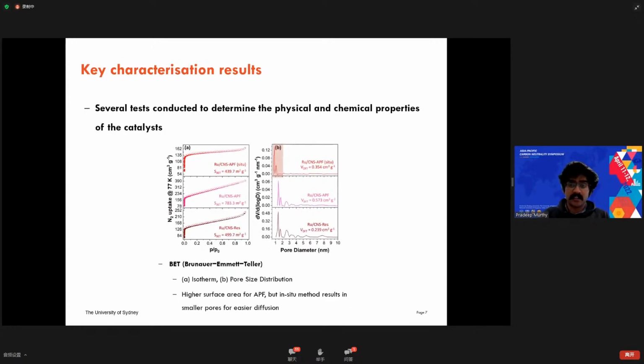We did a BET test. This revealed a higher surface area through using the APF carbon source, but using the in-situ method generated even smaller pores, which would enable easier diffusion of the gases within the structure and therefore more reactivity.